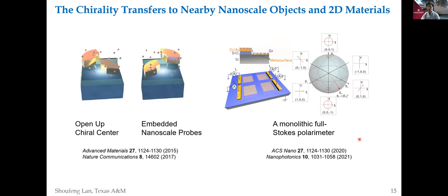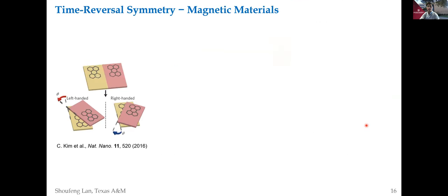Let's pause for a second and ask ourselves, can we push the chirality further to a smaller scale, for example, the atomic scale? The answer is yes. Kim and colleagues, instead of twisting nanostructures, twisted 2D materials, in this case graphene. They observed an optical rotation of around 6.5 millidegrees. Considering that graphene is only atomically thin, this optical rotation is gigantic.